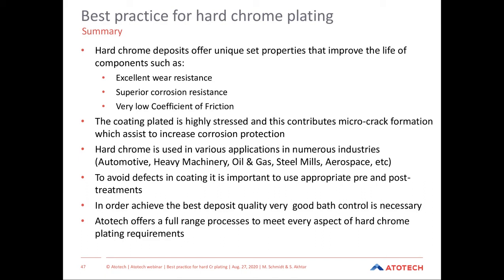Thank you, Matthias. To summarize our presentation here, we can say that hard chromium deposits offer a unique set of properties which assist to improve the service life of the components, such as resistance to wear, which is achieved through the high hardness of the chromium layer, low coefficient of friction, and high crack count in the deposit, which can retain oil for lubrication. Superior corrosion resistance, which is achieved by the preparation steps of the substrate surface prior to plating, and the optimum crack count number produced by the best operating parameters of the plating process, as well as